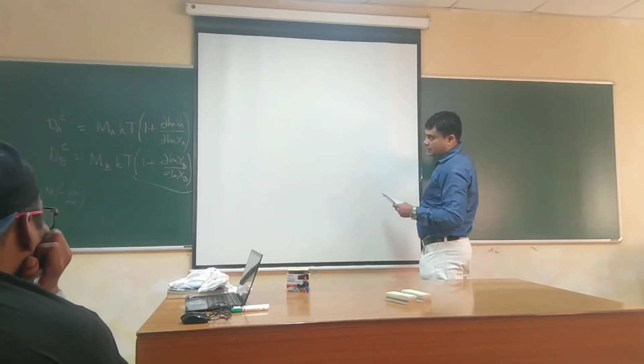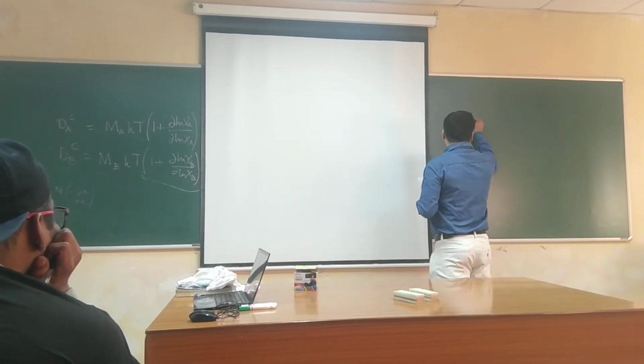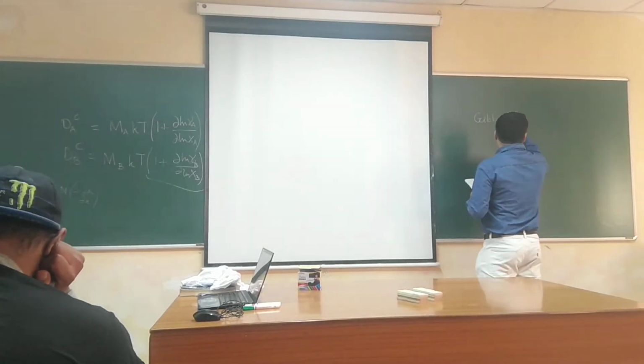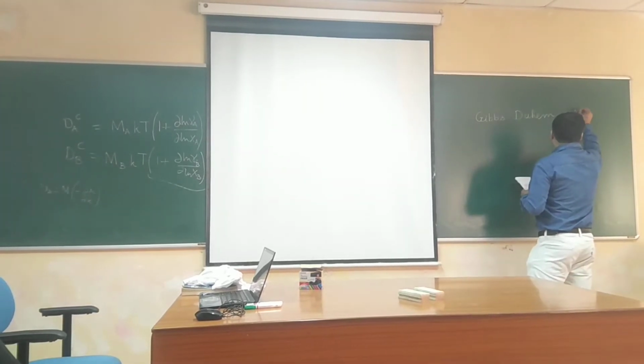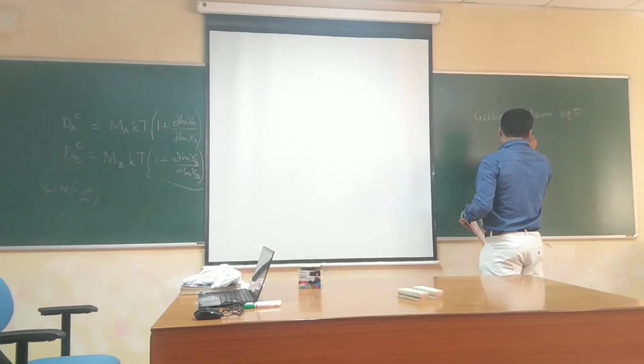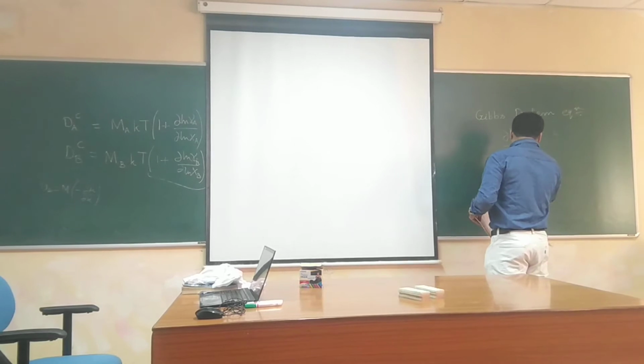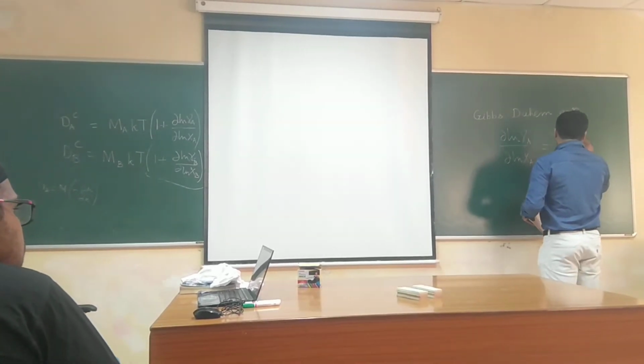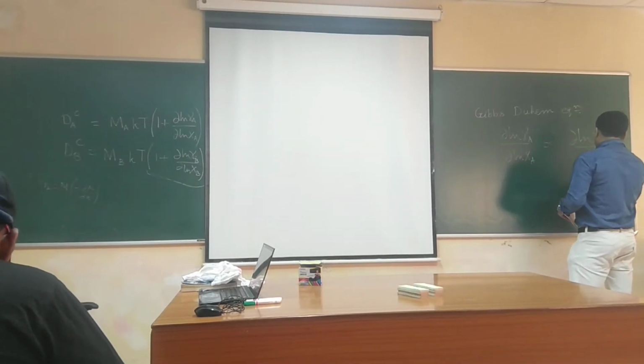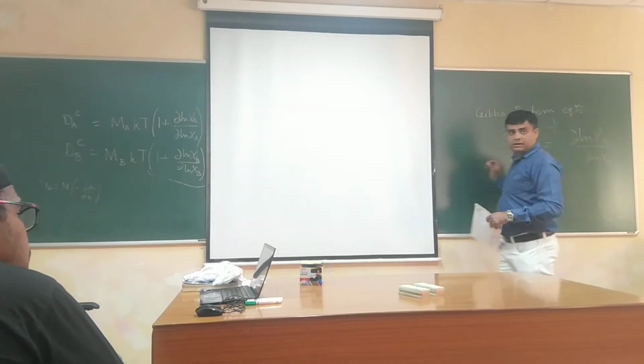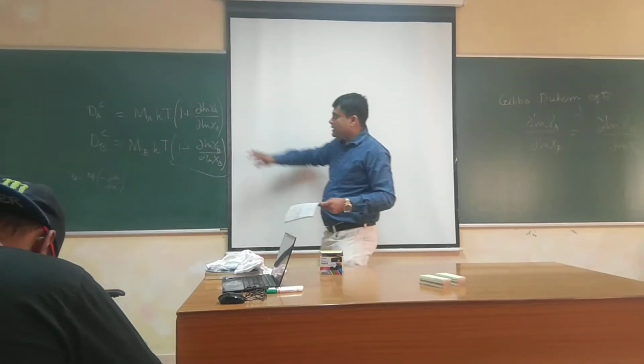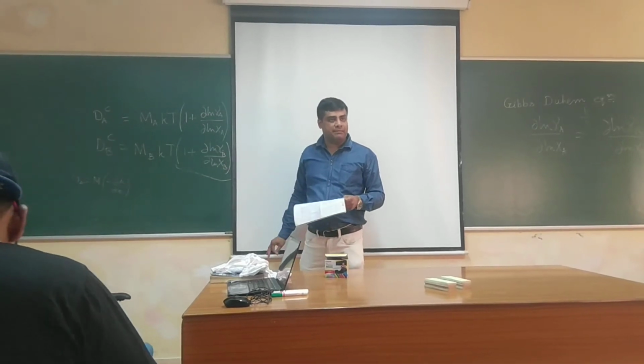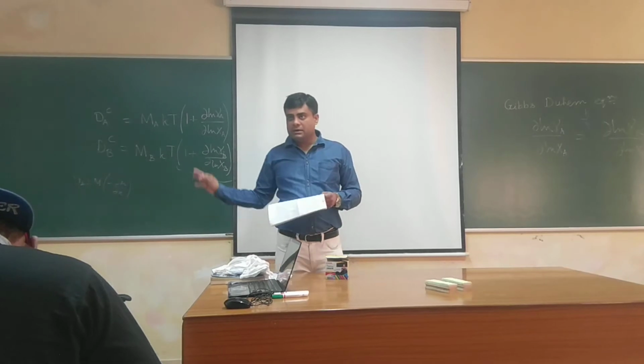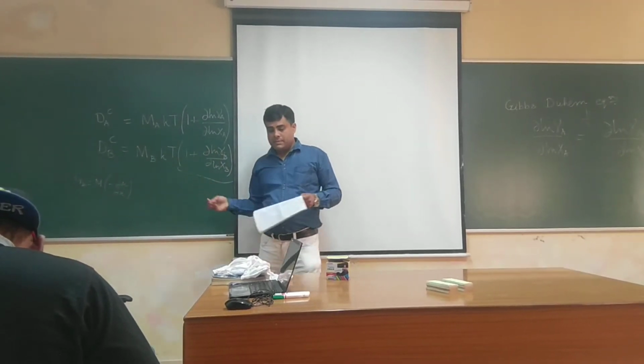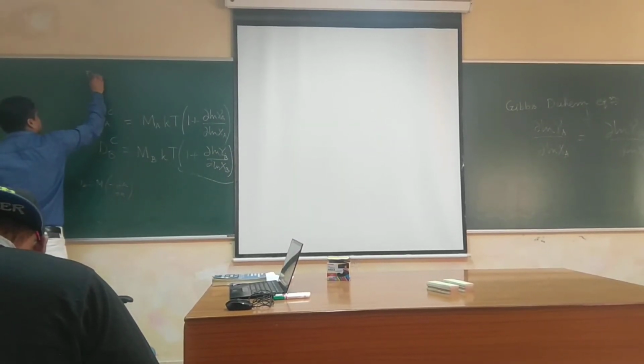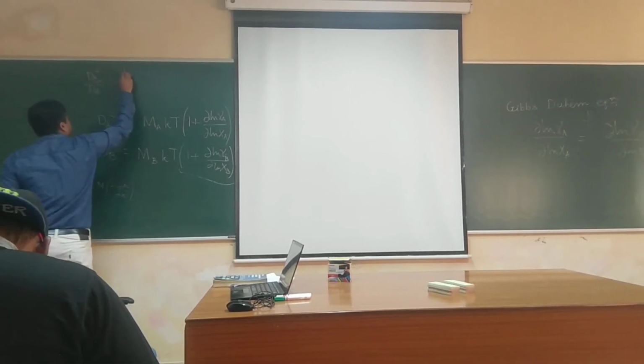So from Gibbs-Duhem equation, from thermodynamics, we get that for different components, this del ln gamma over del ln x are equal. So for A should be equal to del ln gamma B del ln xB. So that comes directly from thermodynamics. So if that is the case, the thermodynamic factor for different components are same at a particular composition. At a particular composition, thermodynamic factor which is within the bracket is same. So we can say that DA over DB is the ratio of the mobilities.